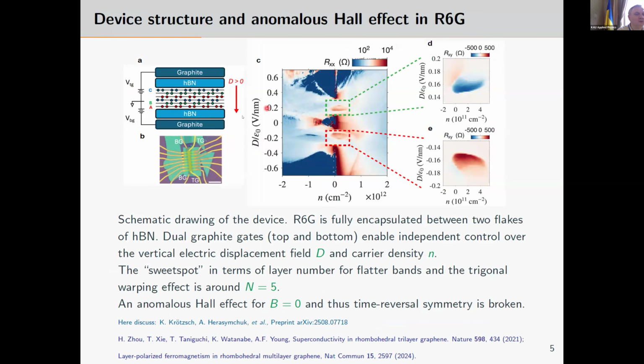And here I show a picture from an experimental paper done with colleagues. They studied 6-layer graphene. As people usually invent abbreviations, like I remember from high temperature superconductivity, YBCO and so on, here R is rhombohedral, 6 is the number of layers, G is graphene. So this structure is encapsulated in hexagonal boron nitride, and done in the standard graphene science double gate setup. So what does it mean? We can tune the gate voltage on one gate and the voltage between the gates. We can tune the carrier density independently and the electrostatic field perpendicular to the layers. So those are both tuning parameters.